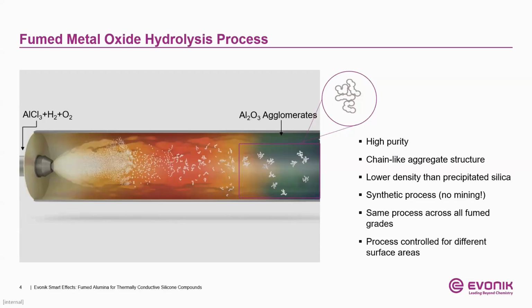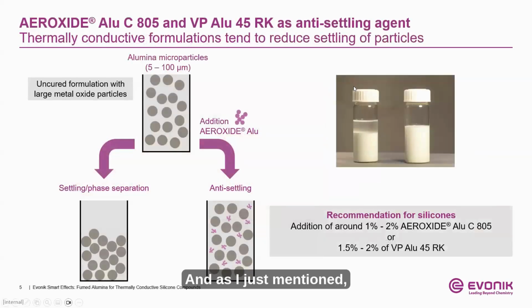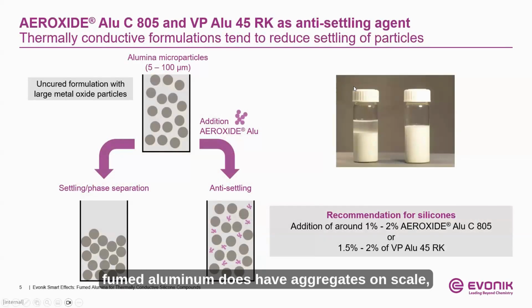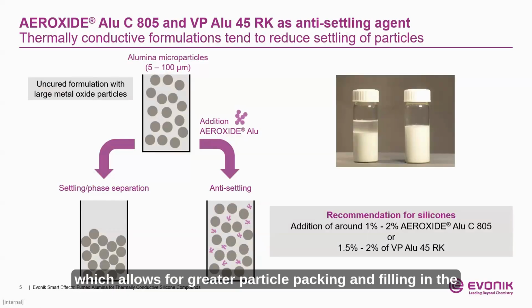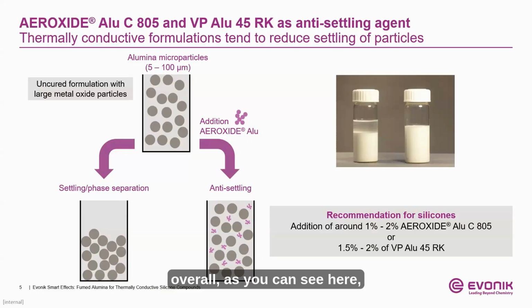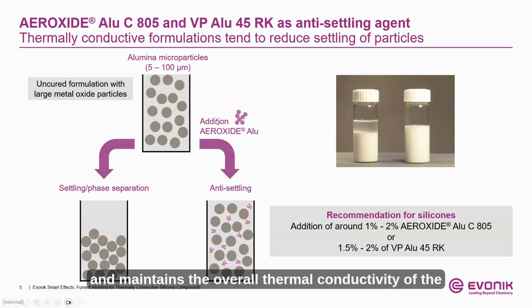aggregates. And as I just mentioned, fumed alumina does have aggregates on the nanometer scale, which allows for greater particle packing and filling in the gaps between much larger spherical alumina particles. This supports better transfer of heat through the system overall, as you can see here, and maintains the overall thermal conductivity of the system, which we'll discuss in a few slides.